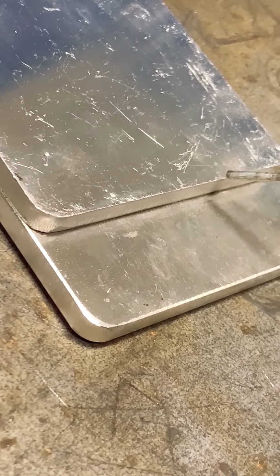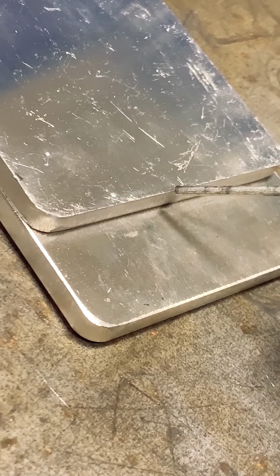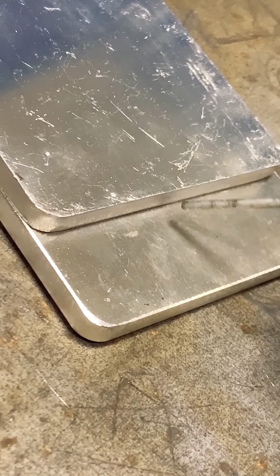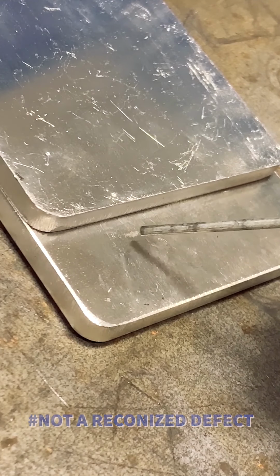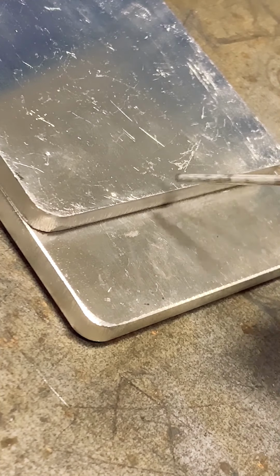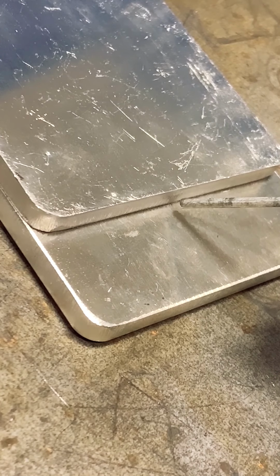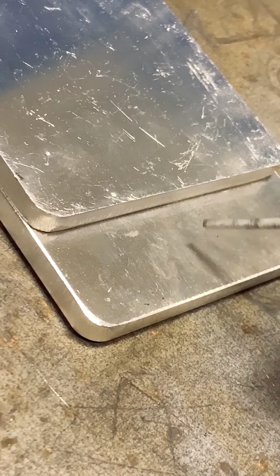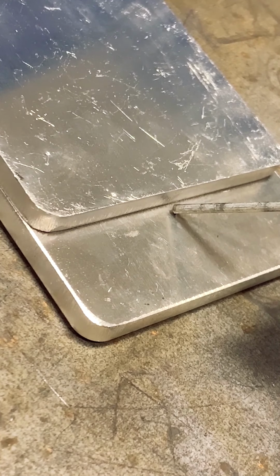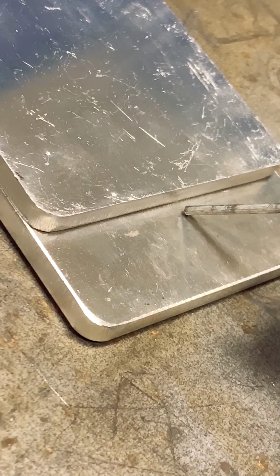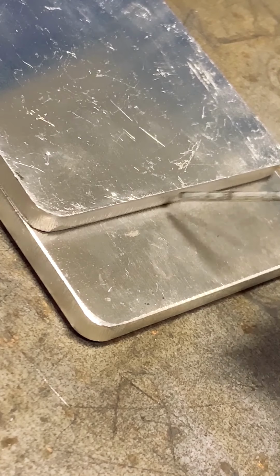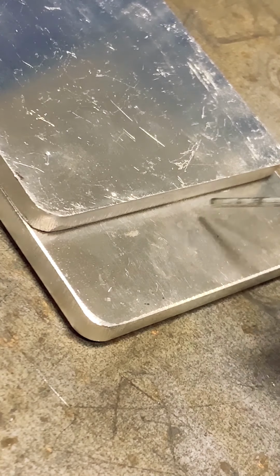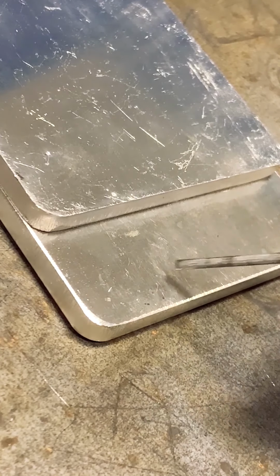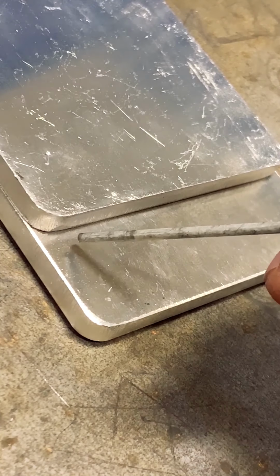Specifically in this lap joint, if I have my electrode too high on this top piece of metal right here, I pull too much of this material, and gravity takes hold and bloops it on down here. So I should be able to see that I'll get some cold roll or some overlap on this bottom toe of the weld, and I'll undercut really heavily here. Shooting straight in the middle in this case might end up eroding this shoreline, as I like to call it, even more. I may want to do probably either the diameter of an electrode, if not half the diameter of an electrode, away from the wall for my placement on joint, so that I can successfully burn in some of this edge a little bit, but also add some filler material to backfill this space as I erode away a little bit of that shoreline right there. And then I won't get such a raggedy profile right there.